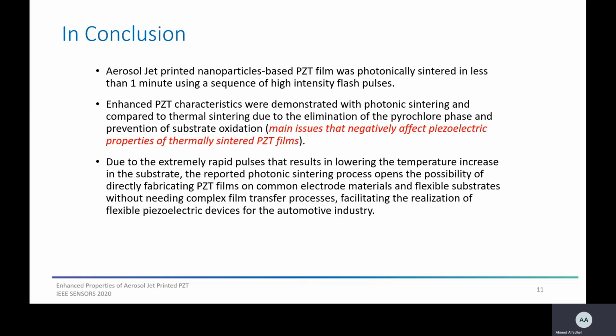Due to the extremely rapid pulses that result in lower temperature increase in the substrate, the reported photonic sintering process opens the possibility of directly fabricating PZT films on common electrode materials and flexible substrates without needing complex film transfer processes, facilitating the realization of flexible piezoelectric devices for the automotive industry.